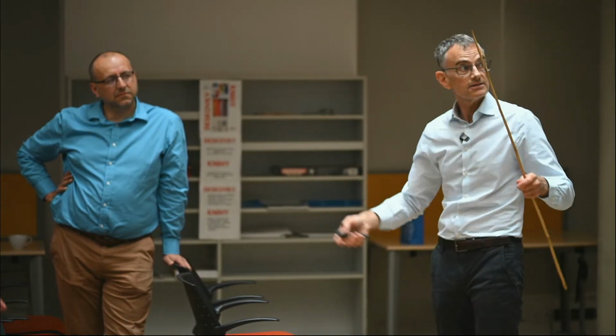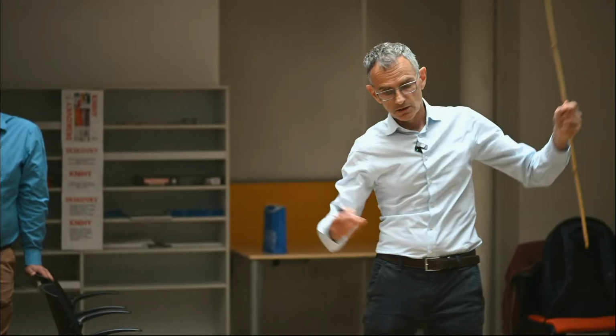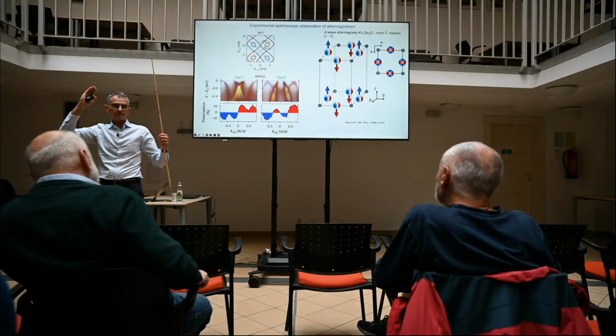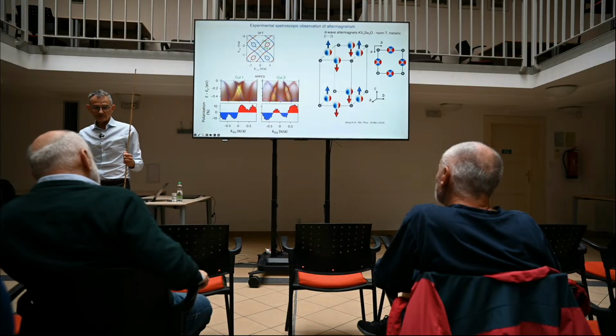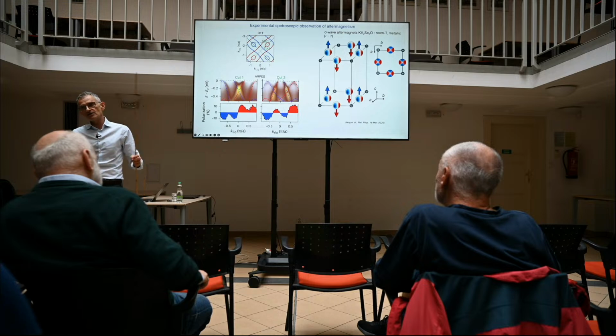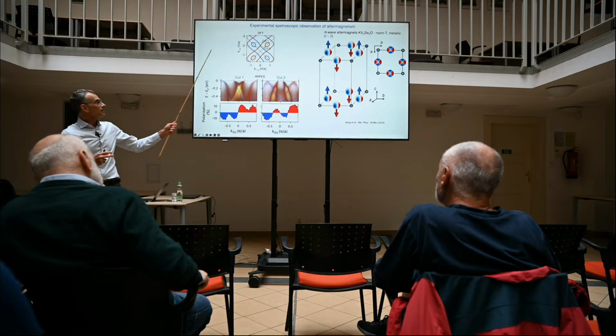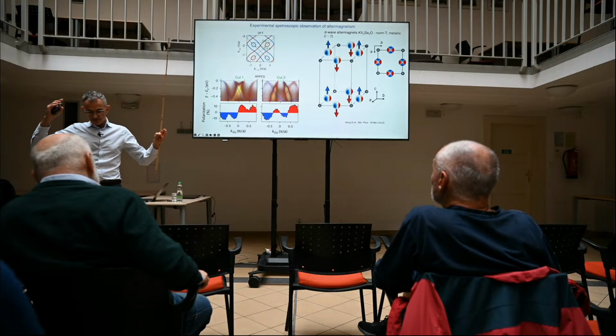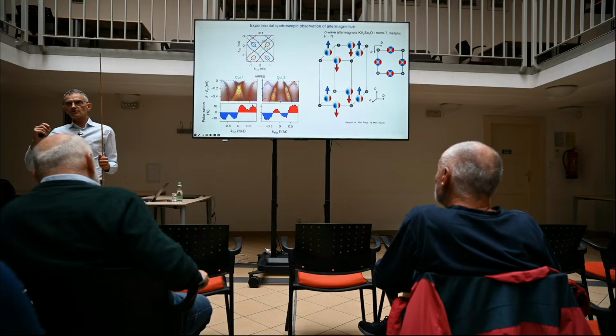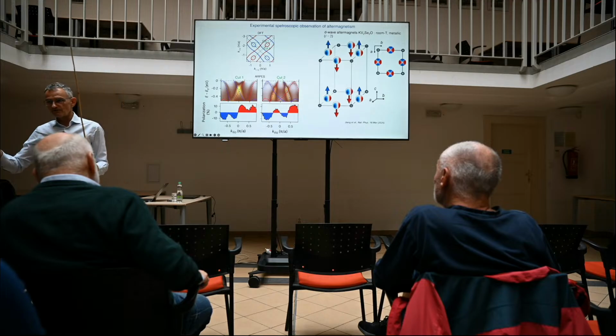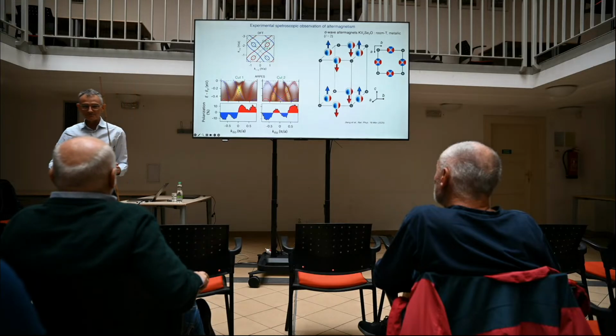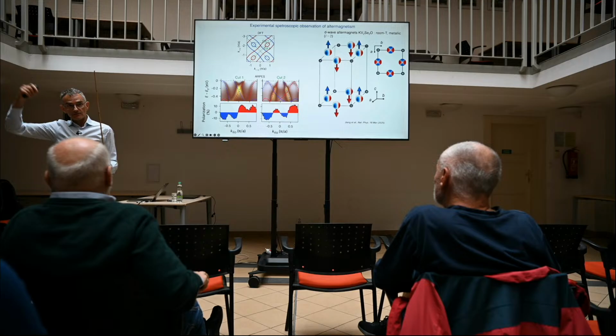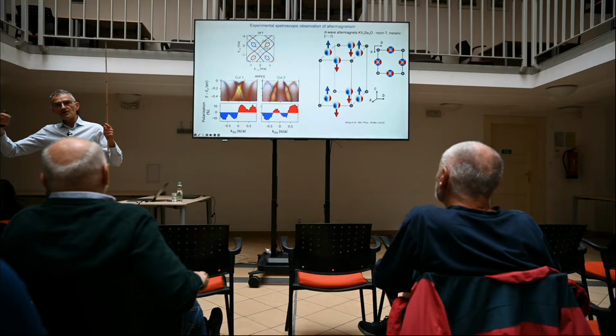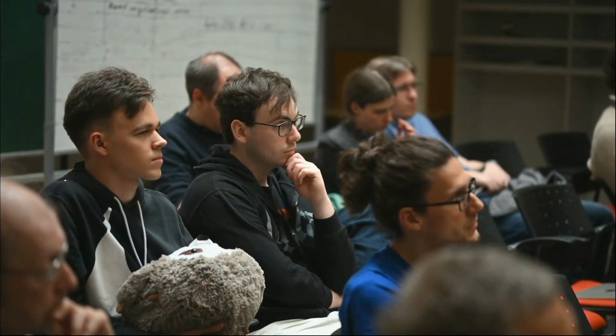So you can have altermagnets which look like this, which basically have only two so-called nodal, or spin-degenerate, Fermi surfaces, and the symmetry corresponds to d orbitals. So we call these d-wave altermagnets, in analogy to d-wave superconductors, it's all the same type of symmetry. Now, in other types of crystals, you can have four nodal surfaces, which would correspond to what in atomic physics is called g-wave. We don't know much about g-wave. We typically end with f-wave because g-wave are not typically occupied orbitals in atoms. But it's the angular momentum L equals 4 spherical harmonic. And you can also have i-wave, which is L equals 6. So you can have d, g, or i, or 2, 4, or 6 nodal surfaces, depending on the crystal structure,